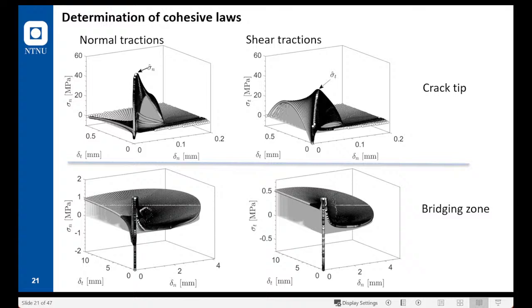The slide I have shown before was an example only for mode 1. In real life, we have to calculate the tractions versus the openings for any phase angle, and that results in 3D surfaces for the normal traction and the shear traction. And since for damage-tolerant composite materials we have a large fracture process zone, we actually have to derive a separate cohesive law for the crack tip and a second one for the bridging zone. Once we have defined these surfaces experimentally, we can introduce this material law in a finite element code and model the behavior of a composite structure, in this particular case a composite wind turbine blade.